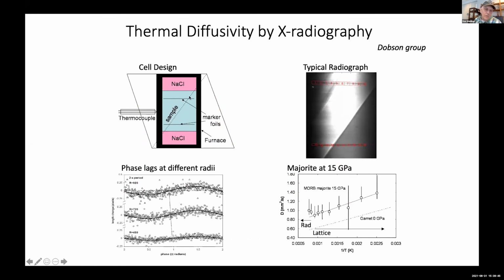Using these sinusoidal variations, the Dobson group designed experiments where they put markers in the sample, just a line going through the center, and sinusoidally heated it, with the heating from the furnace on the outside. By looking at the phase relations at different positions along here, the length of the sample between the lines being a proxy for temperature, they concluded the thermal diffusivity. And here's some results for majorite at 15 GPa, as a function of 1 over temperature. And here they move into radiative heat transfer, so that this actually gives them fairly robust results.